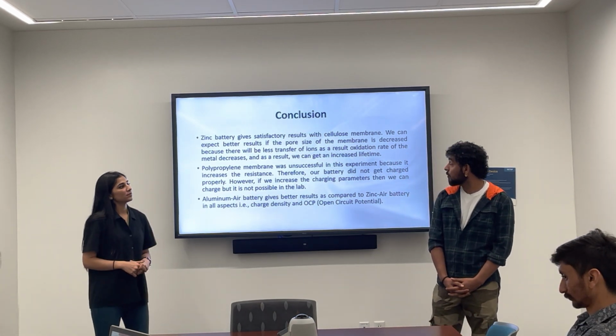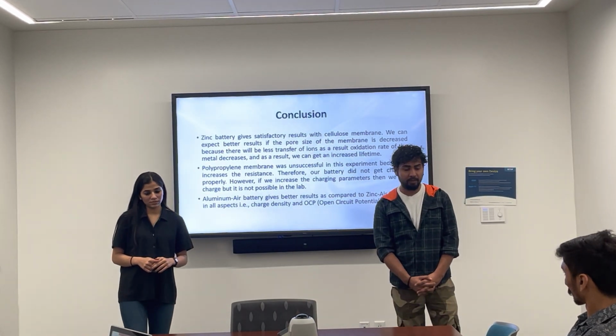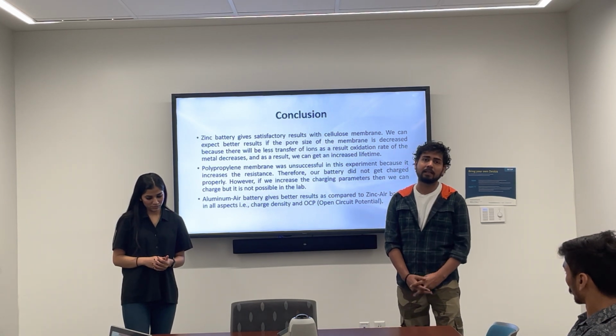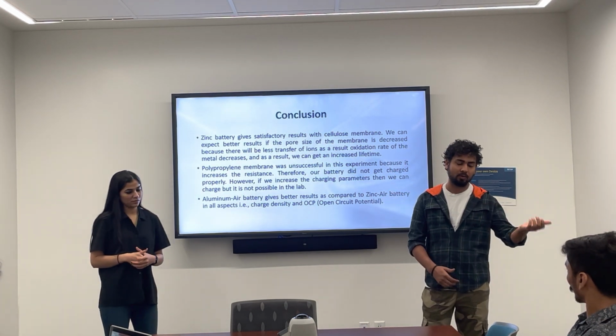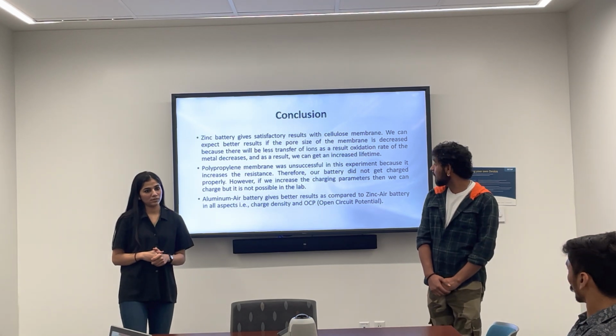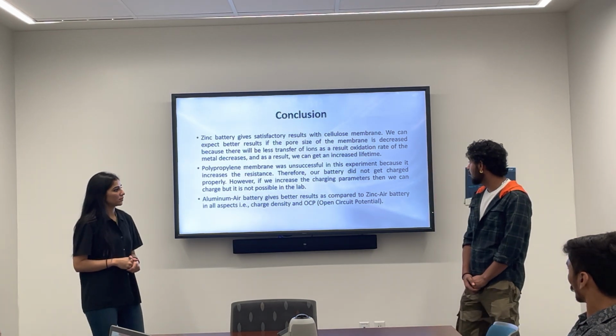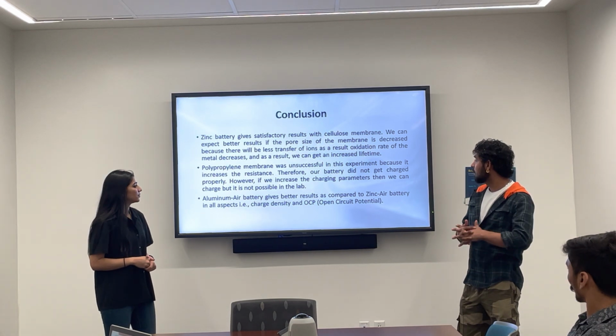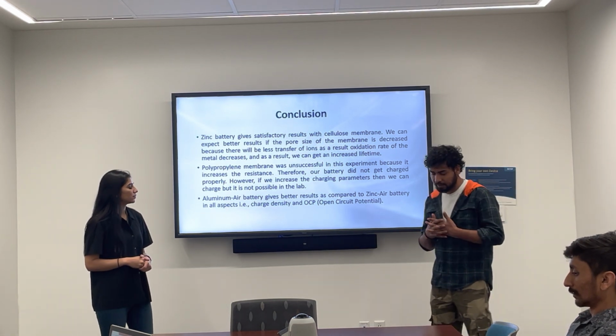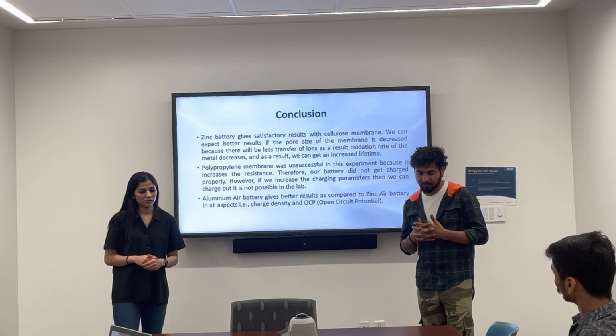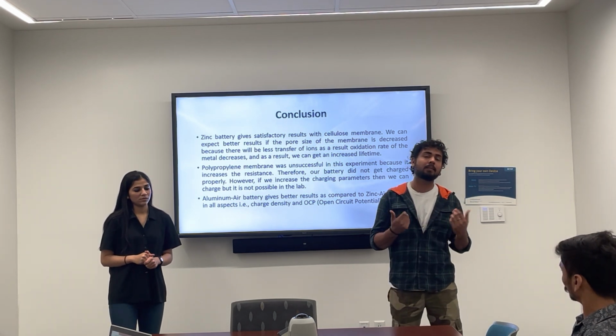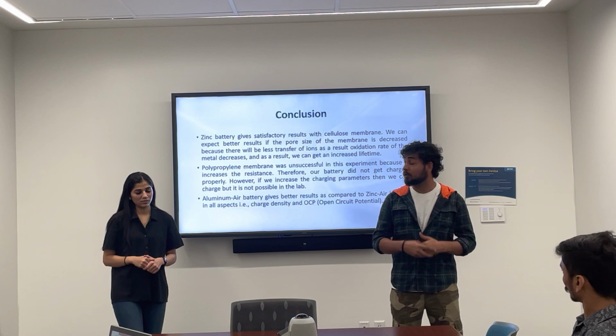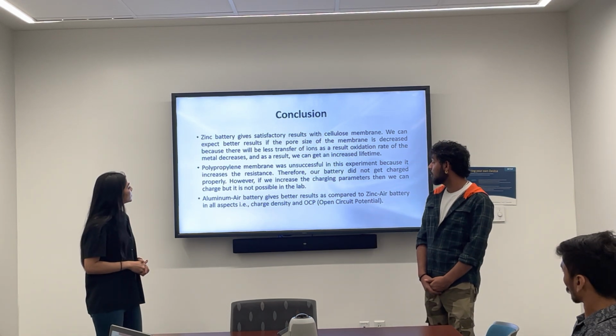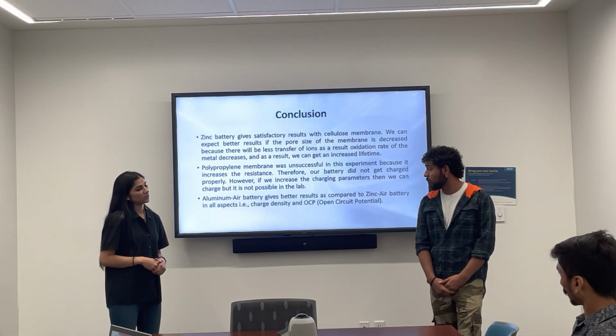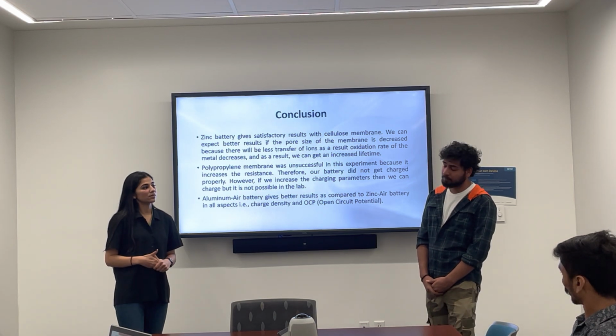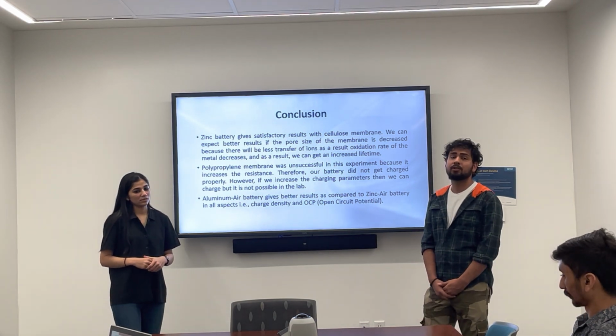For the membrane, we used two types: cellulose and polypropylene. With cellulose, results are better, and we can expect some good news from the cellulose kind. But polypropylene doesn't give us successful results. The reason can be that it increases the resistance. It has a hydrophobic nature, which resists the ions from moving. And the last one is zinc and aluminium. For the aluminium, we are getting better results because it has 3 electrons, more energy.